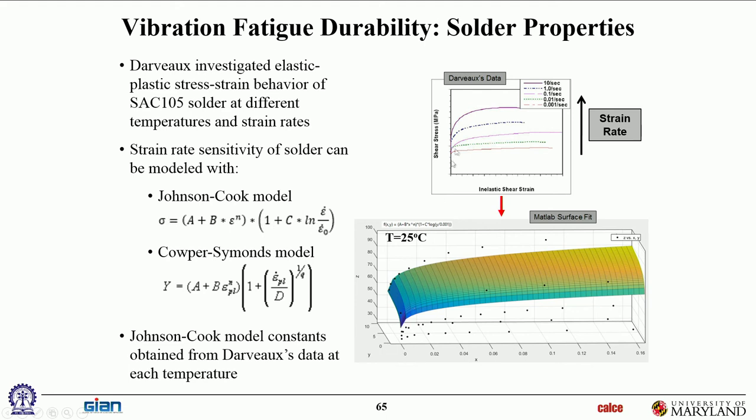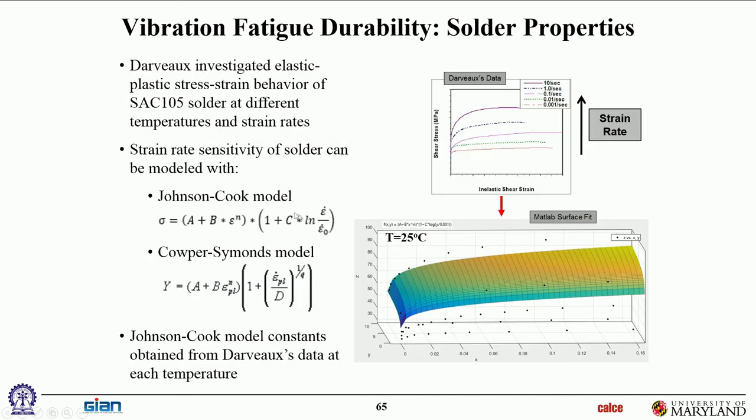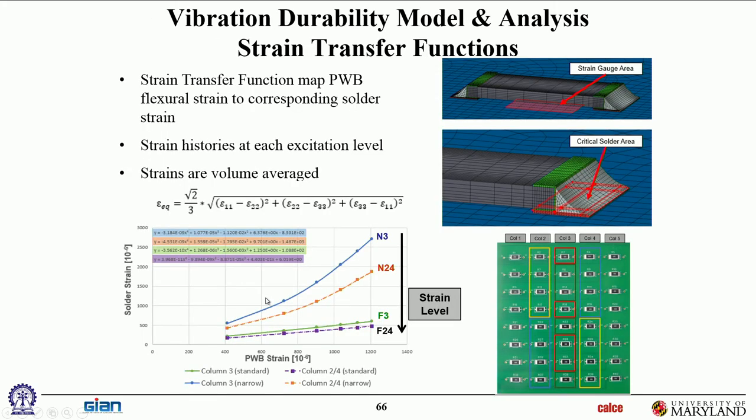So you can see in this graph, low strain rate, this is how it looks. High strain rate, that's how it looks. It looks very different, okay? And this is just a 3D version of that. Stress on the vertical axis, strain on the horizontal axis, and strain rate on the other axis, okay? So it gets pretty complicated, but that's what we are using in these finite element models. We are using those rate-sensitive stress-strain curves.